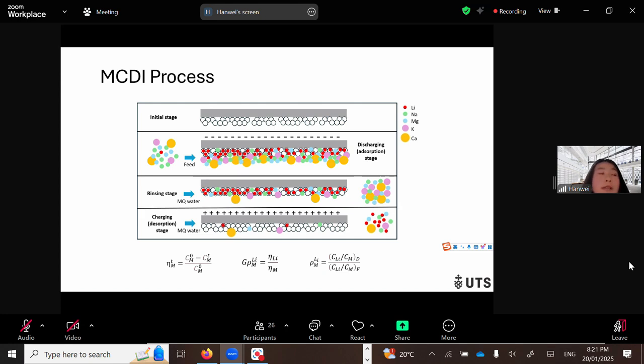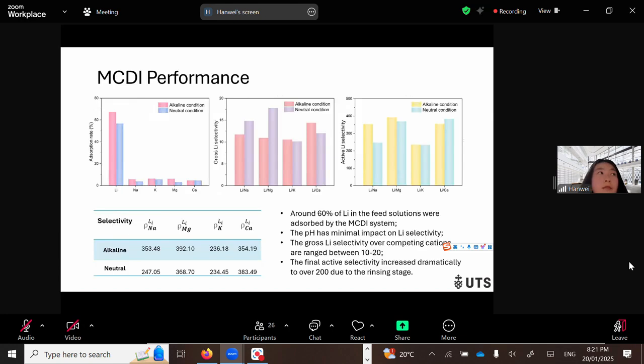To evaluate the performance of this MCDI process, we have the metrics of the lithium adsorption rate, the gross lithium selectivity and the final lithium selectivity. And for the MCDI performance, the result shows that around 60% of lithium in the feed solution was adsorbed by the MCDI system. The pH has minimal impact on lithium selectivity. The gross lithium selectivity over competing cations ranged between 10 to 20. However, with the rinse stage, the final active selectivity increased dramatically to over 200.